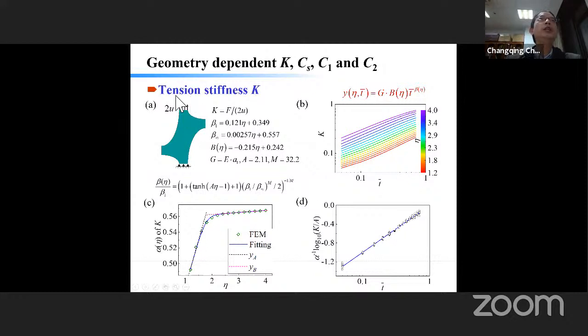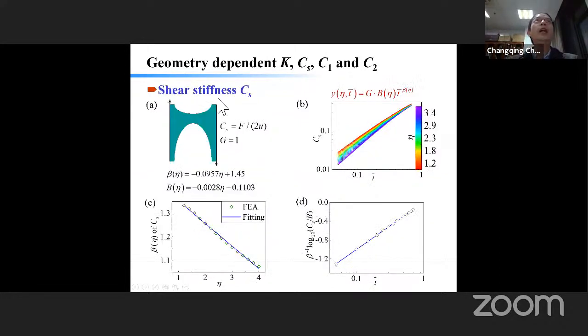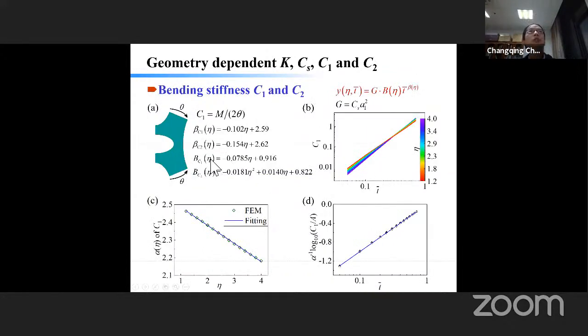Basically, as I mentioned, K is the tension stiffness. If we load the model joint here, we can calculate the stress as a function of displacement. Then we are able to determine K as a function of the parameters A1, B1, and A2, B2. Then we get the formula for K in terms of the geometry of the mechanical metamaterial we just discussed. Here the solid line is this formula, and the dots are the observed results. You can see very clearly that the fitting is quite good. Similarly, we can calculate the shear stiffness and the bending stiffness in terms of the geometrical parameters of the metamaterial.